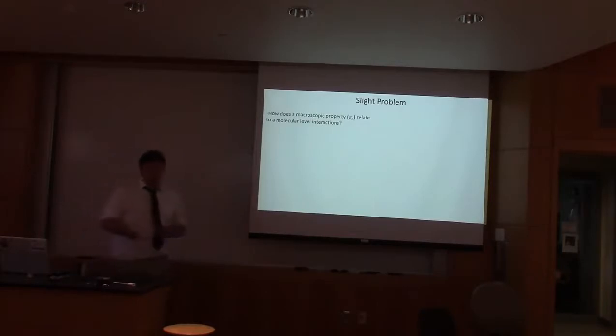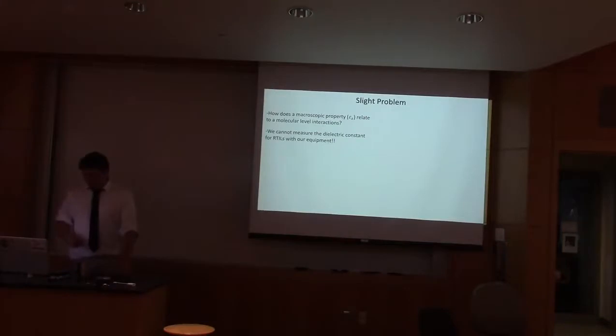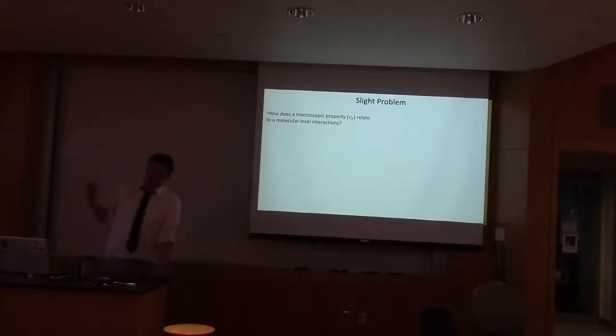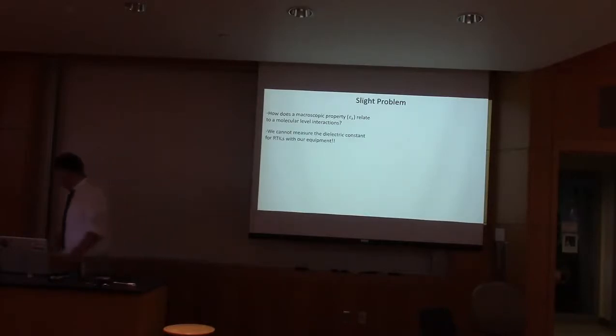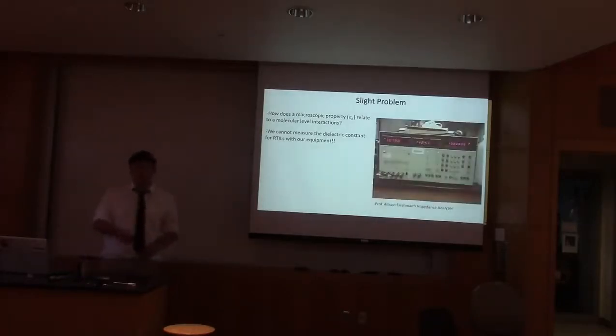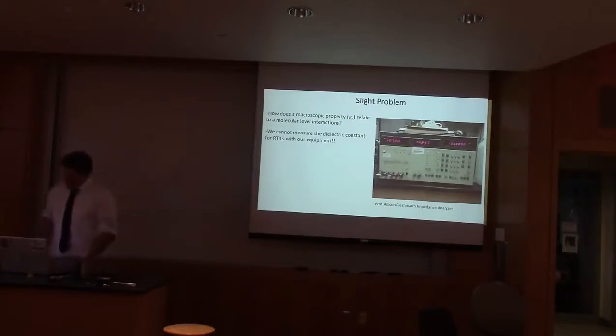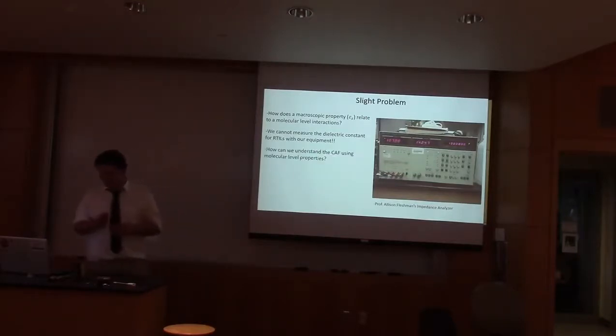Slight problem though. The dielectric constant itself is a macro scale property. We usually associate the dielectric constant with being the overall effectiveness of a material, or the dielectric field of an entire material. And therefore it's hard to understand the dielectric electric field's effects on molecular level transport properties. The other problem we have is that we cannot measure the dielectric constant of room temperature ionic liquids with our given equipment. Our impedance analyzer only goes up to a certain frequency, and it is not sufficient to then calculate the dielectric constant of room temperature ionic liquids.